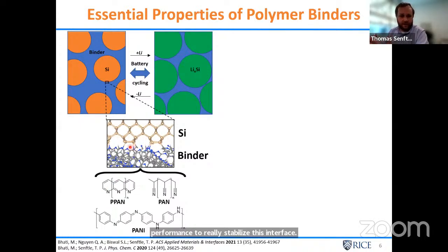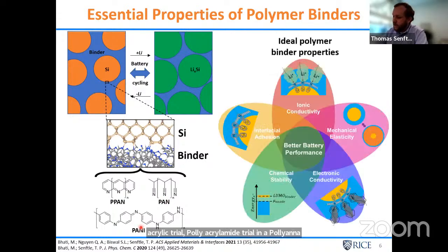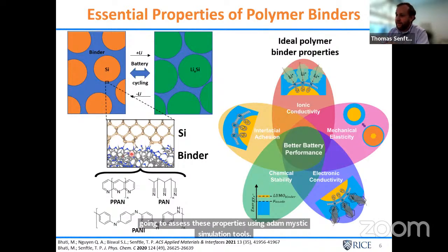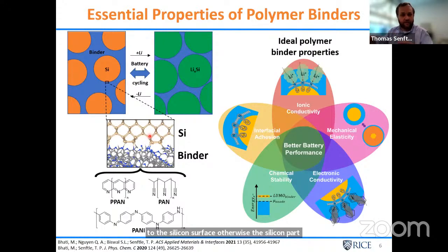So today I'll talk about the comparison of three different binder materials. PAN, pyrolyzed PAN, and polyaniline. And we're going to look at the different properties that each of these binders have, and we're going to assess these properties using atomistic simulation tools. Among them, the ones that are important, the binder has to adhere strongly to the silicon surface, otherwise the silicon particles can migrate around and agglomerate, and you lose surface area, you lose the effective active material.